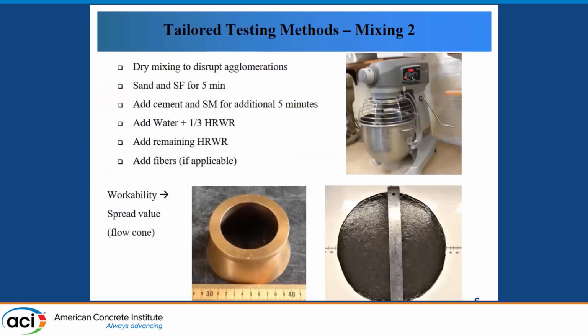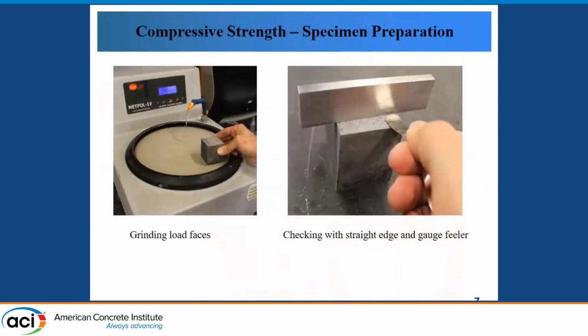When mixing UHPC, we usually use the tabletop mixer displayed here and follow the strict mixing protocol for enhanced consistency. The workability was measured by regular spread cone. Compressive strength has been tested using 2 by 2 inch cubes. Prior to testing, the load surfaces were ground until passing the quality control. We check the surface smoothness with the straight edge and gauge filler because we do not want any roughness in the loading surfaces, which can lead to misleading compressive strength.